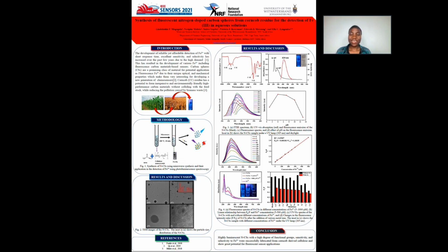In this study, fluorescence quenching will be utilized for the detection of iron 3+ in aqueous solution using nitrogen-doped carbon spheres that were synthesized from cellulose nanocrystals derived from corncob residue. These nitrogen-doped carbon spheres were synthesized using a one-step microwave synthesis at 180 degrees in 10 minutes. This was then purified and stored in the refrigerator for further use.